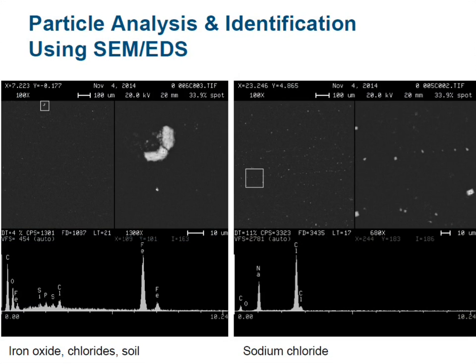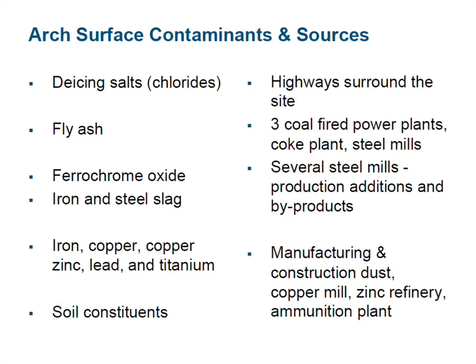And here are a few pictures. The one shows iron oxide with a little bit of chlorides and some common soil contamination. The other is sodium chloride, obviously de-icing salt. But this summarizes what we found. There were very small amounts of de-icing salt and very minute levels, far too small to ever have picked up with anything but this type of test kit on most of the arch. But it's very, very small, which isn't surprising because of the highways.